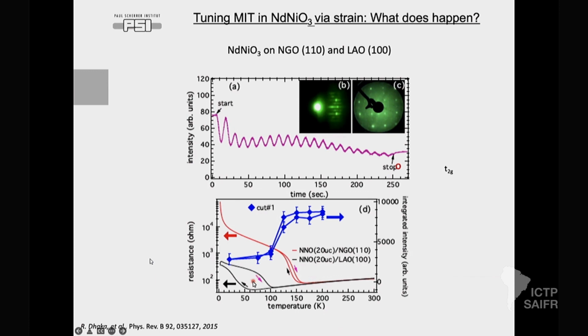In the literature, this kind of metal insulator transition is happening in a way that is not at the same time everywhere in the system, right? So you have regions which are still maybe metallic, some of them more or less metallic, and some of them are already insulator. In ARPES we are averaging those domains, and we see just the spectral weight going down. This is one of the explanations. In the resistivity, until all of these patches go to insulator, you will not have a total insulator. It will of course increase resistivity, but it will not yet turn into a complete insulator. I see.